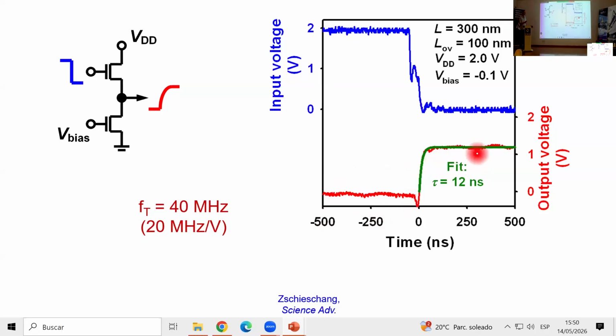And then by fitting an exponential function to this response here, we can extract the characteristic delay, and that is in this case 12 nanoseconds, and that corresponds to a transit frequency of 40 megahertz. Okay, so these transistors have a transit frequency of 40 megahertz. That's the highest transit frequency that's been achieved for organic transistors fabricated on flexible substrates.